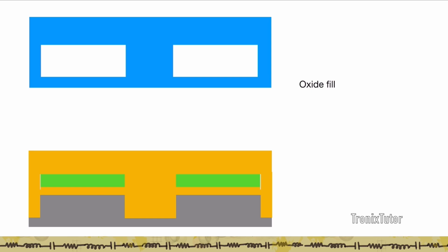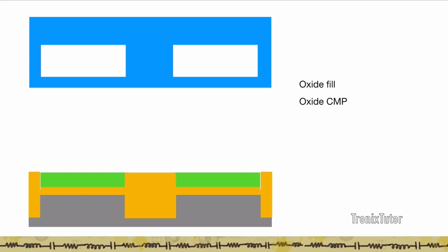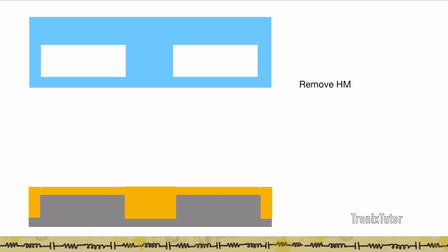Once the oxide is filled, the next step is the oxide chemical mechanical polish, where the hard mask, or the nitride, is used as an etch stop for the CMP. And this, as I mentioned, has created an electrical isolation between these two adjacent transistors. Right? So the first step is we have marked out which area we're going to build the transistor, and we have created an isolation between the two transistors. The next step now is to form the wells.